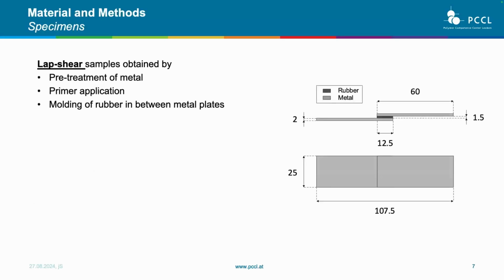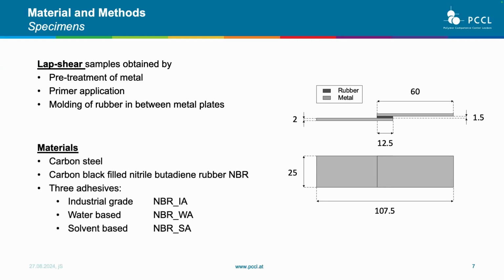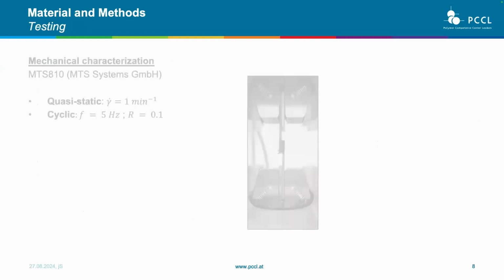So to do this, we produced this kind of specimen. You can see here the geometry that we chose. It's inspired by adhesive standards and adapted for manufacturing and producing these samples with rubber. We did a pre-treatment of the metal, as usual, the primer application, and then molding of the rubber in between the two plates. As materials, we used carbon steel, and for the rubber, a carbon black filled nitrile butadiene rubber. And then we used three different primers: an industrial grade one, a water-based one, and a solvent-based one, to see if we can really catch some difference in the adhesive strength with this kind of specimen.